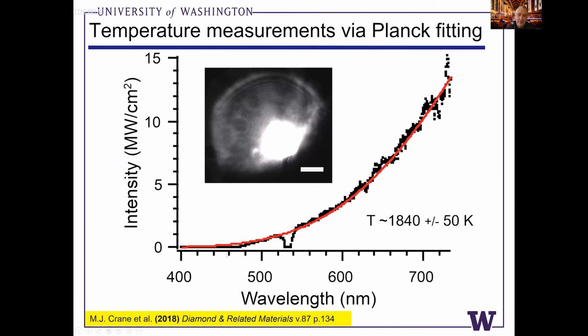So this is a spectrum just to illustrate how we're measuring the temperature in this experiment. We shine a high intensity CW laser, ytterbium fiber laser, typically on the amorphous carbon. We get white hot Planck emission spectra, extremely bright Planck emission. And so we can disperse this emission onto a spectrometer, fit the UV-visible region to Planck's function, and extract a temperature that typically ranges between 1500 Kelvin and on the order of 2000 Kelvin. So we can reach temperatures, at least for brief time points, that are much higher than what can be reached in, say, a multi-anvil press. It's really challenging to reach these types of really high temperatures.